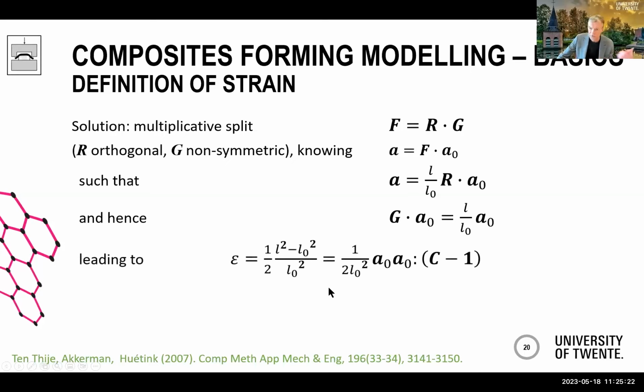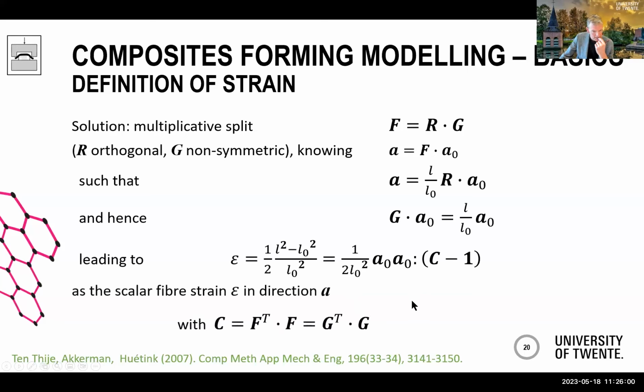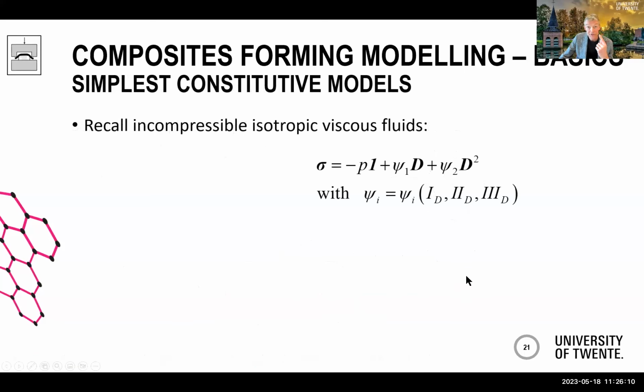Well, from this, if you go through the continuum mechanics, you can figure out that from the right Cauchy-Green tensor, you can compute nicely the strain in the fiber direction. And once you implement this, you have a formulation which correctly, exactly describes your fiber strain. Yeah, and this is just the standard definition of your right Cauchy-Green tensor. Okay, so that for strain.